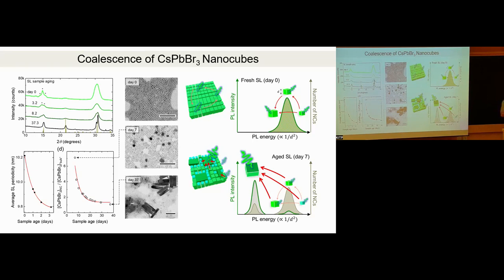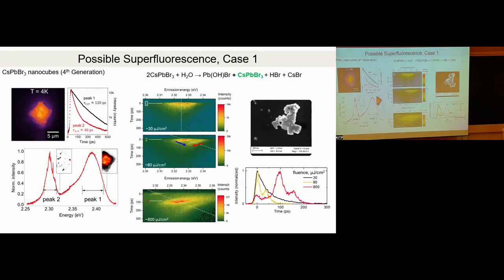However, there are two instances when I don't know if we saw superfluorescence, but we might have. The first possible case is that when we leave these superlattices in air, small nanocubes form bigger and brighter particles. In this case, you have a double peak emission with an accelerated photoluminescence decay. Moreover, when you look at these bigger particles on their own as a function of excitation fluence, you see in the time decay plots interesting oscillations that might be interpreted as superfluorescent, or perhaps some other effects.